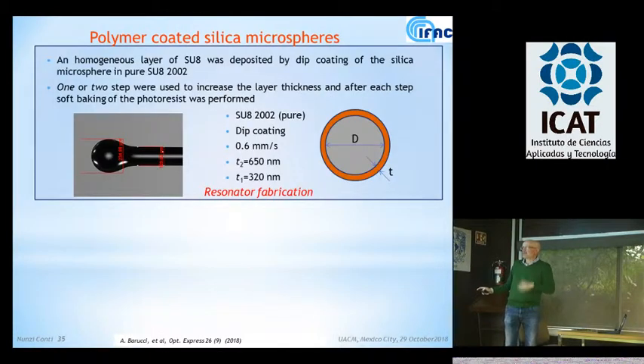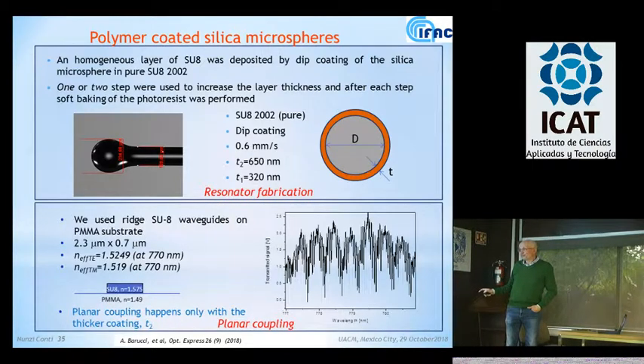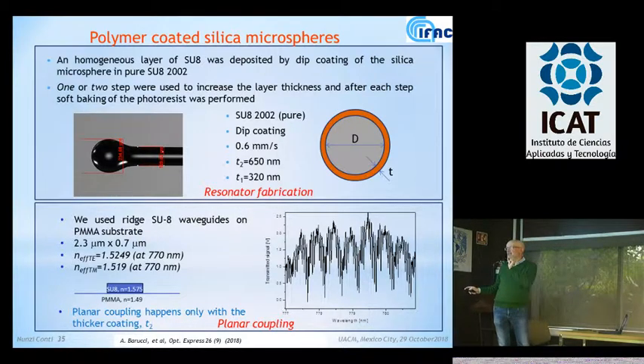And so we developed a system, which I'm not describing here, to demonstrate that you are actually coupling light into the coating. And we did this by using simply a rib SU8 polymer waveguide, and demonstrating that planar coupling could happen only in coatings that were thick enough to have one mode inside the coating itself.